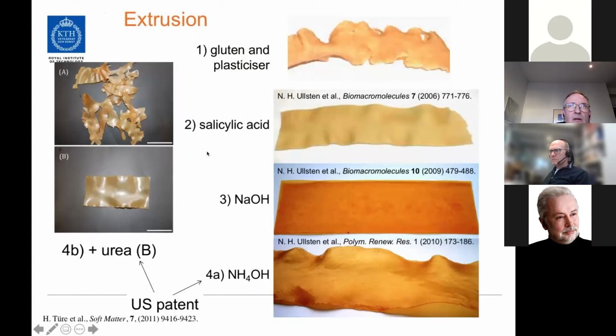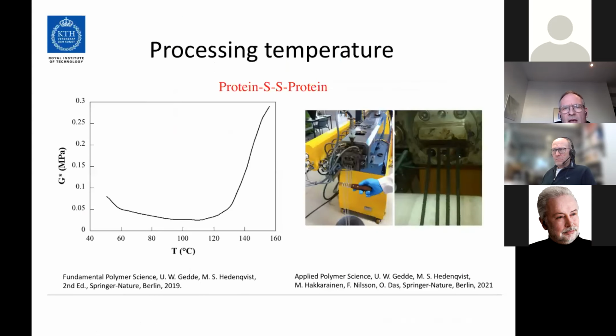Extrusion is generally more difficult than compression molding for this type of materials, but it all depends on the additives you put in and the parameters to choose. If you look at the sample to the left, lower part there, there's very nice and high quality films that we've been producing from extrusion. If you don't put something else into the material, it is rather difficult to extrude because it has a relatively high viscosity, although it's shear thinning like other polymers. This is a big difference from pure thermoplastic materials.